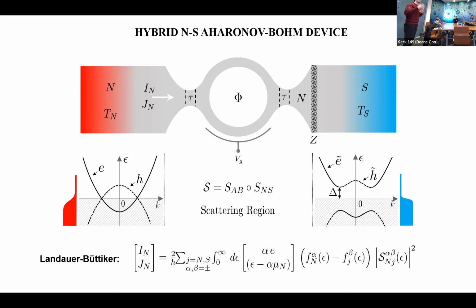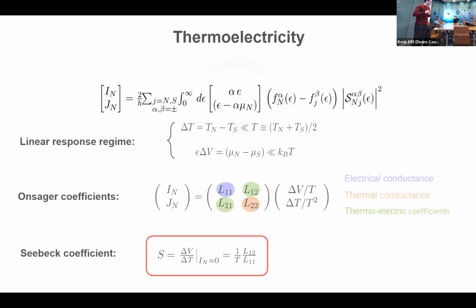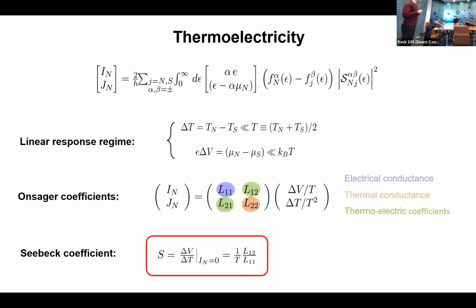Now, the first thing that we want to verify for our system is if it really works as a thermoelectrical device, namely as a system that produces electrical current under the application of a thermal gradient. And indeed, we did this. We investigated this property by considering first the so-called linear response regime, which happens when delta T, the thermal gradient, and delta V, the electrical bias, are very small with respect to the thermal energy, k_B T. If this is the case, you can linearize the Landauer-Büttiker currents, and you can express these currents in terms of the so-called Onsager coefficients, L11, L12, L21, and L22, which really correspond to the electrical conductance, the thermal conductance, and the thermoelectrical coefficients, which are related by the so-called Onsager reciprocal relation. In our case, they are exactly the same.